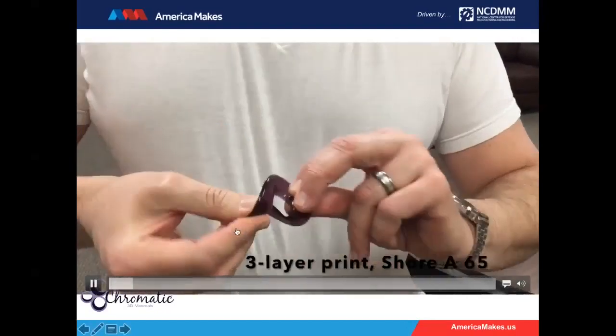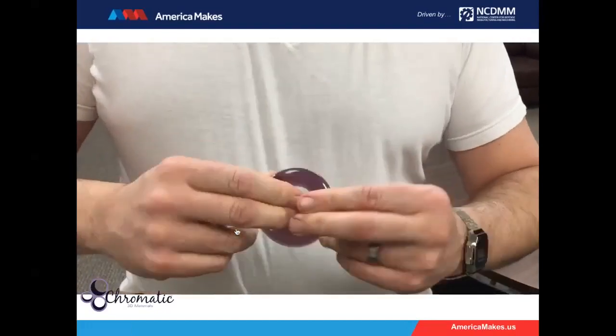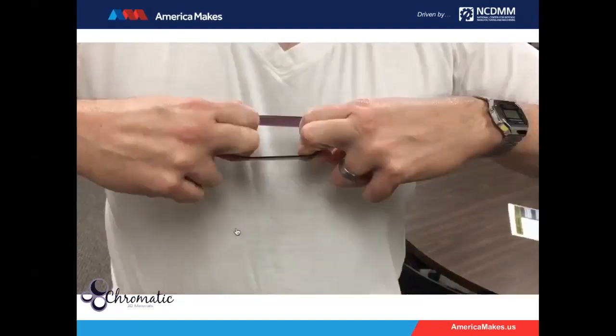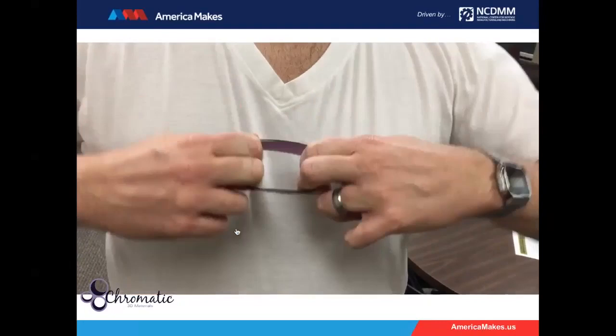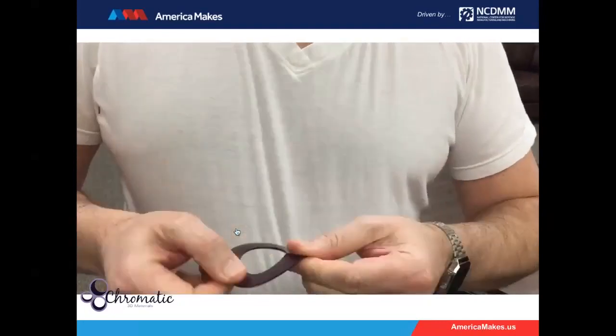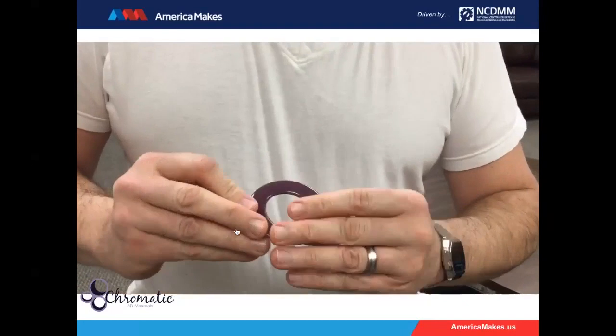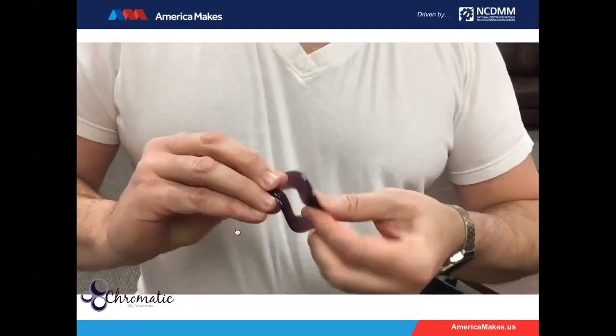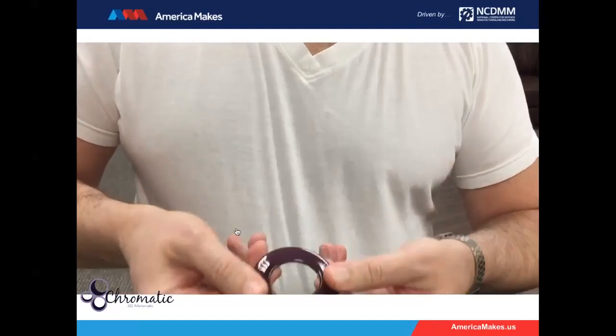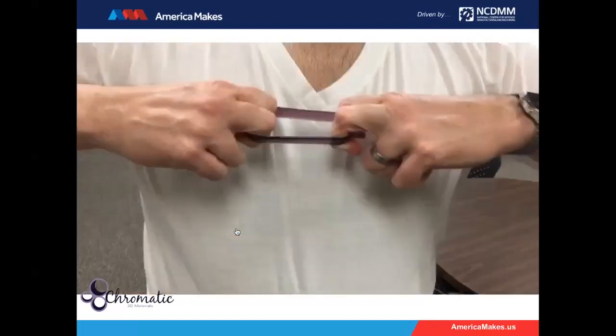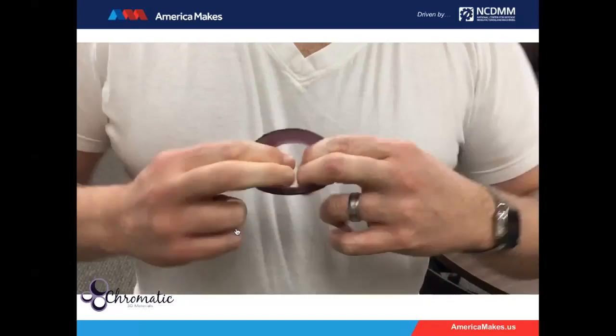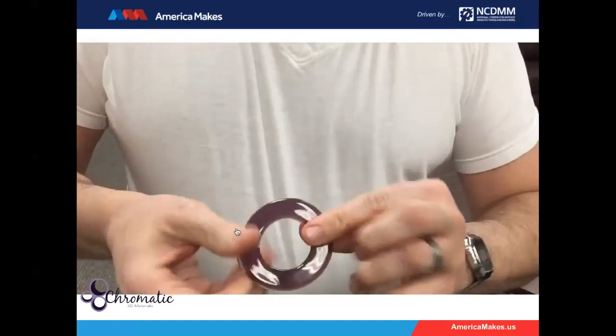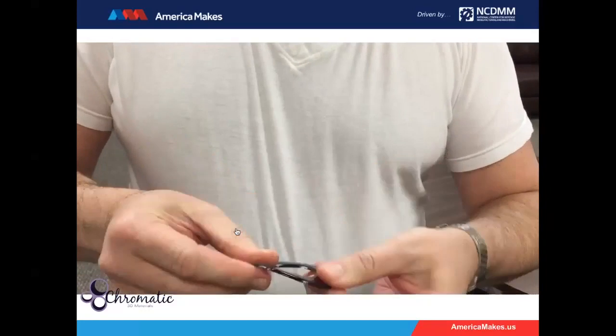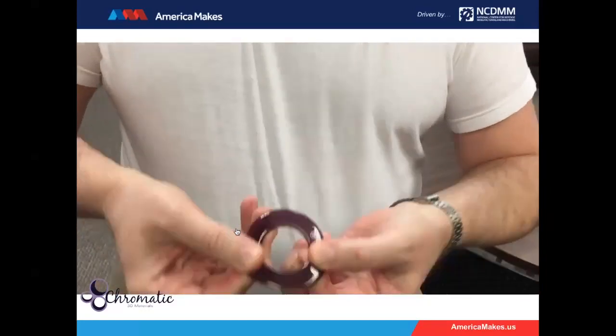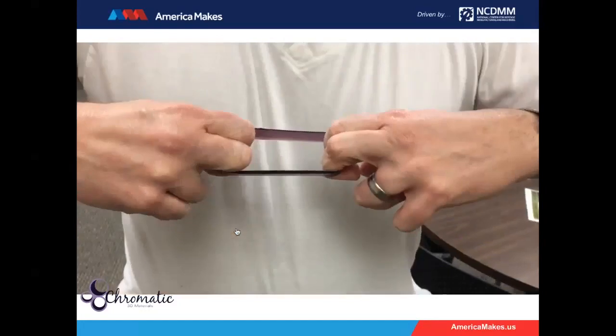Now here, I'm going to show you some of the results that we can get with this. So this is a very simple 3-layer print. It's about a Shore A of 65, so it's pretty flexible, but it's also really strong. So we've been able to get that same effect, get the same properties that we expect of a polyurethane, where it's flexible, but you can just keep stretching it over and over again. And these rings will just return right back to their original dimensions after the stress. So we can stress it over and over again, and because we've got that great hydrogen bonding, because we've got great chemical bonds just holding that part together, it's a part that is strong.